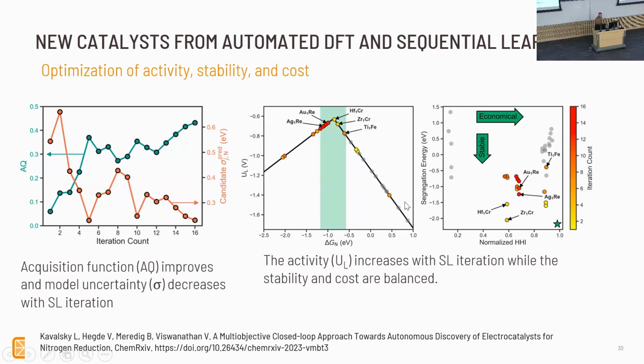But this is the very common volcano plot you see in catalyst papers. This is the activity of the catalyst with regards to the process you care about. And on the x-axis is basically the free energy for the reaction that you're trying to catalyze. And you can see you want to be in this window here. And as we get later in the iteration count, as the color gets redder, you get closer to the peak of that volcano, which is where you want to be.